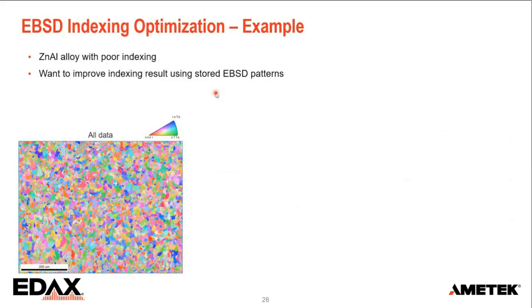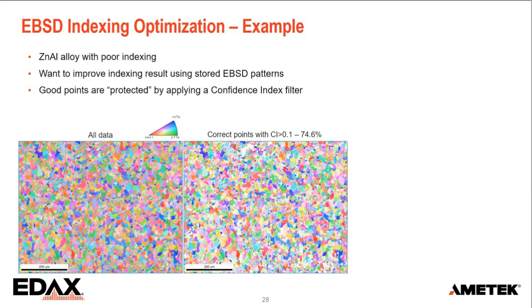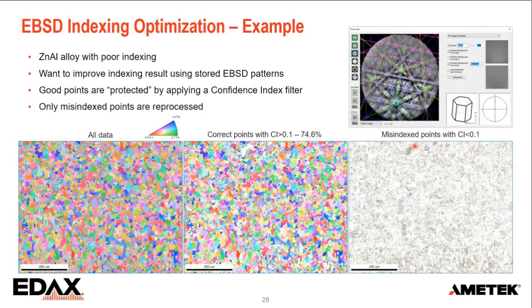Now, first of all, here I have a zinc aluminium alloy, try to index that, and let's see how we can use the EBSD patterns to improve it. What I have here, I just use a CI filter. I only show the good ones, it's about 75%, but then I flip that. So now I'm only showing the bad points. I take a pattern, I optimize the image processing and the indexing for those patterns that refuse to index in the first place, and I'm only going to change those. I'm not going to touch the points that properly indexed in the first place.